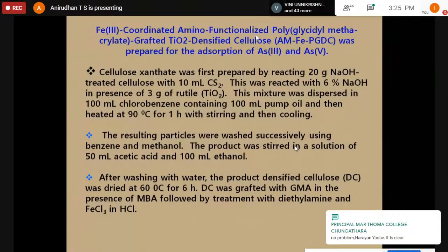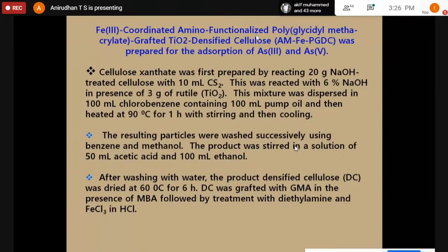So our idea is to prepare a strong anionic exchanger to remove arsenic 3 and arsenic 5, which exist as oxyanionic species in wastewater, in acidic or basic media. We want to introduce that type of stable material because your wastewater is acidic or basic in nature. When you treat acidic wastewater with your material, the material may be damaged. This is the problem we face with the materials reported in the literature nowadays. We have introduced this material with high efficiency, and we can repeatedly use it several times for removing arsenic 3 and arsenic 5 from any industrial wastewater associated with arsenic.